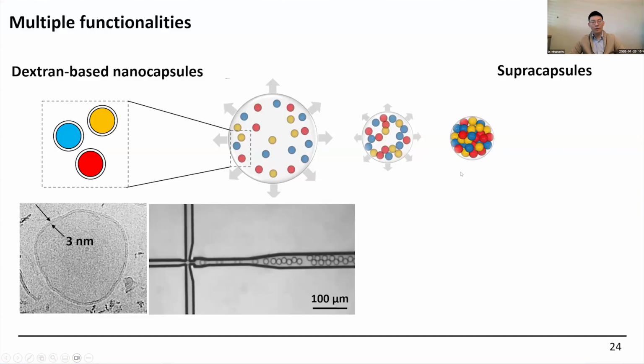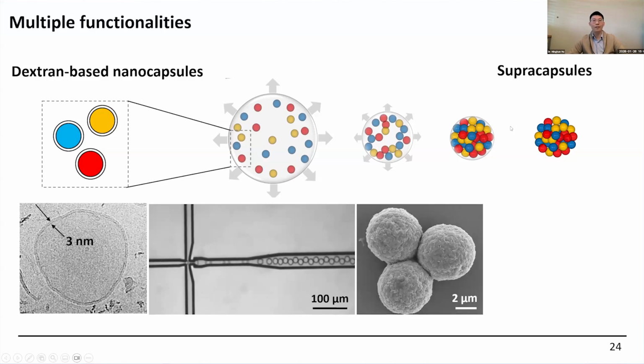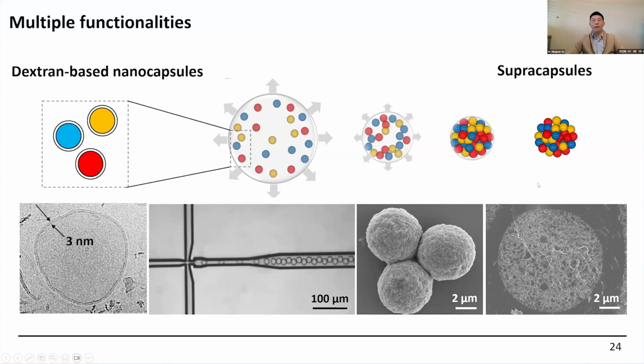And then we do the same trick. We evaporate it, then the nanocapsules will self-assemble into this cluster structure. Because they are made from nanocapsules, we call them supracapsules instead of superparticles. And these are the SEM images we can see. They are nicely packed with each other. And we also cut it open to see the inner structure. We can see they are fully covered with these nanocapsules.